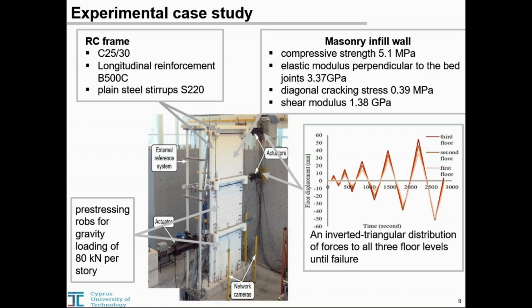You can see the class of concrete that was used, with a compressive strength of concrete equal to 27.8 megapascal, and the modulus of elasticity of concrete was 24.1 gigapascal. You can see the class for longitudinal reinforcement, and also the class for transverse reinforcement. The transverse reinforcement for concrete members was of class S220 with a mean value of yield strength equal to 270 megapascal.